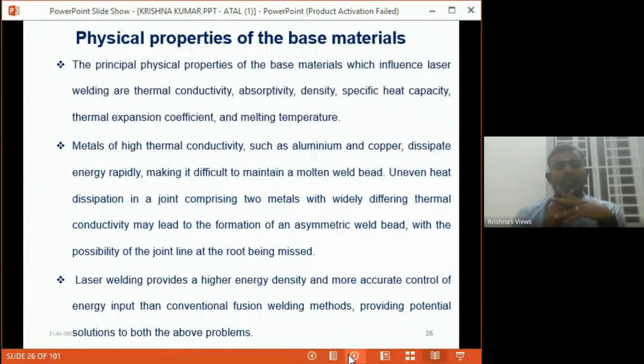Metals of high thermal conductivity such as aluminum and copper dissipate heat rapidly, making it difficult to maintain a molten weld bead. Uneven heat dissipation in a joint comprising two metals with widely different thermal conductivity may lead to the formation of an asymmetric weld bead. That is, one side will be a molten pool, another one is solid. So that will break in the welded joints. So we should analyze after the trial, and take remedial actions to get better joints.